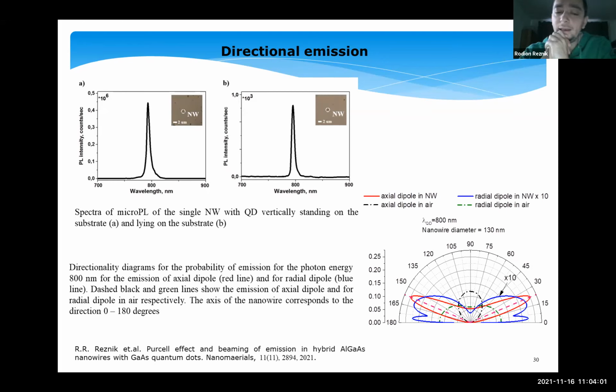And then with the help of Mikhail Kolesievsky, we built some theory, and you can see here in this corner the directional diagram for such structures for aluminum gallium arsenide nanowires with gallium arsenide quantum dots. And you can see that even if we don't have the fundamental optical mode, HE11, we will have directional radiation at about 22 degrees to the axis of the nanowires. So we have directional emission from these quantum dots.